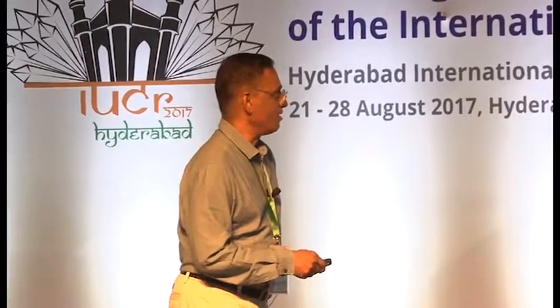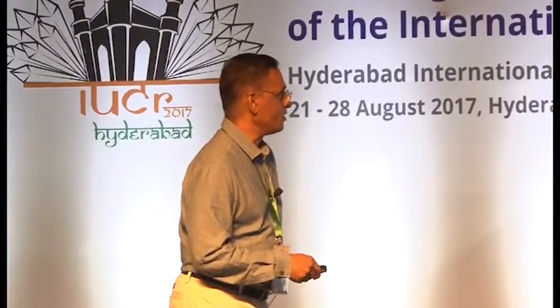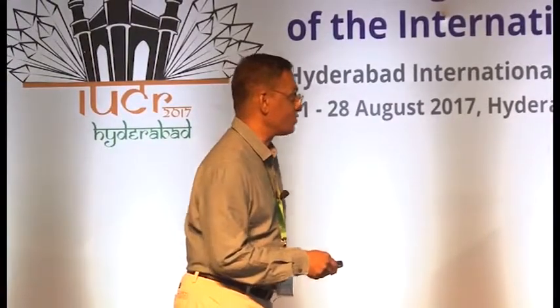In this case, when we were trying to make pellets to record IR, we found that some of the coordination polymers react with KBr on grinding, especially when you have acetate and trifluoroacetate. You need to be careful. You better use Nujol, and don't grind them with KBr.